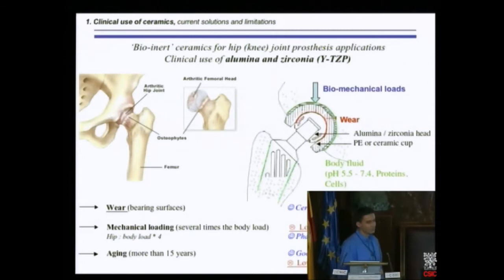You have several times the body load which is applied to the hip joint. For example, for the hip joint, only by walking, this is 4 times the body load. For the knee joint, it can be 6 to 8 times the body load. So that's quite significant and demanding mechanical loading. So as we said before, alumina has a modest crack resistance, and that's why YTZP was used in the 90s because of phase transformation toughening.